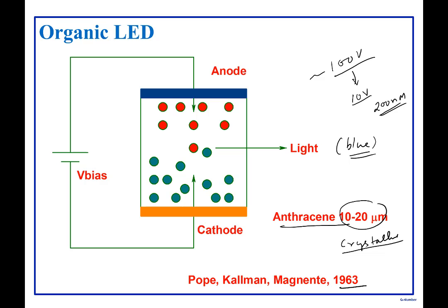But what you can do is take this material anthracene, and these are highly volatile materials. So you can heat up anthracene and it would evaporate. If you take a crucible, put anthracene into it, heat it up, and put your glass on top, anthracene would evaporate and stick to the glass. So you can form a 200 nanometer thin film, very nicely. But what would happen to that film? Amorphous.